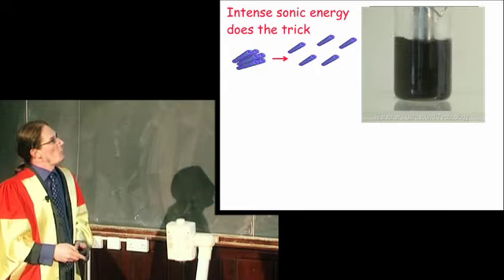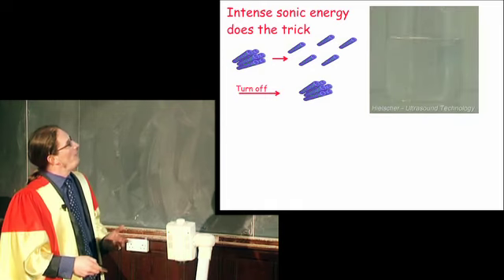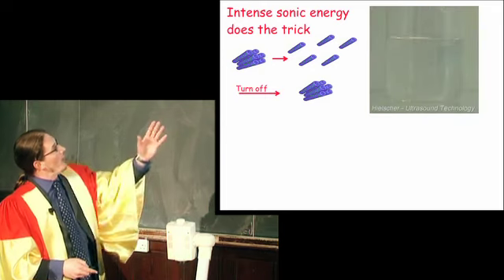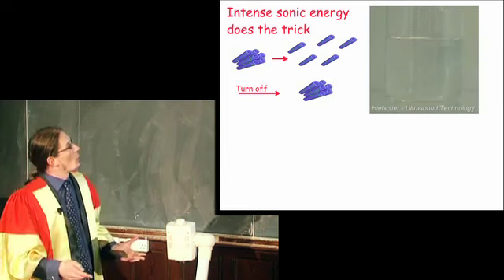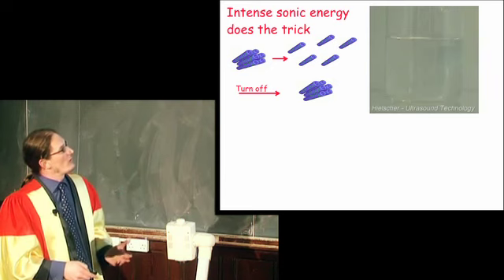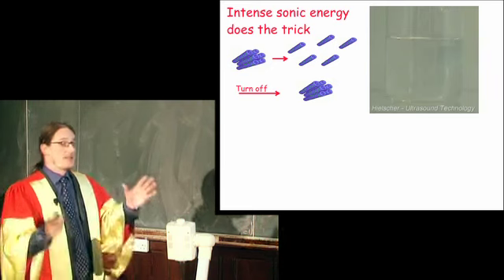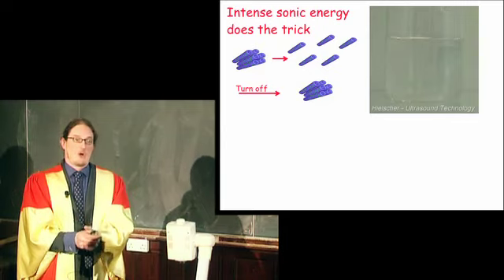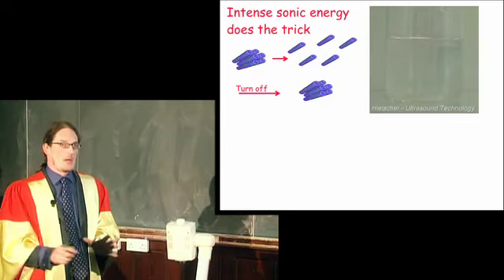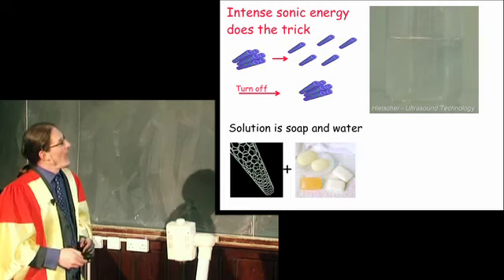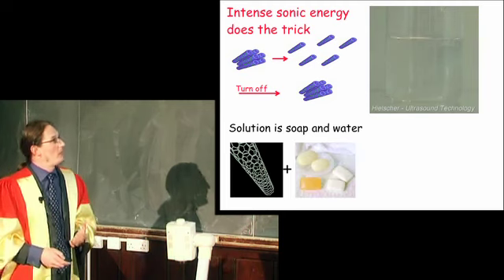The problem is that when the tip was on, the bundles had broken up into individual nanotubes, but when I turn the sonication off, they stick right back together. So we've made some progress, but we haven't solved the problem. And it turns out that the solution to this problem was very simple.